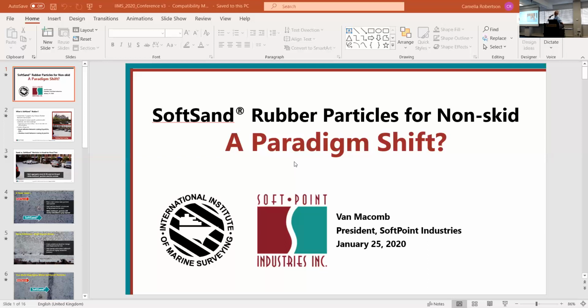And in general, the boaters are gravitating towards a much larger particle. If you look at the samples I have out there, the medium grade is quite a bit larger than what you're seeing with some of the plastic granules. And then the one out there is a 1/4 inch rubber particle that we're putting down on some work boats, like some lobster boats up in Maine. So I think it's a very different approach when you have a granule that's more compatible with your coating and your bare feet.